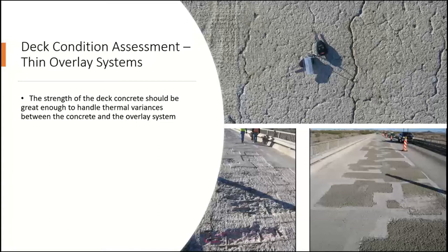We knew that this deck concrete did not have what we thought would be 250 PSI tensile strength, which is kind of an industry standard for concrete strength to retain a thin polymer overlay system for a good long time. We knew it then. When they came and did all this patching, we knew we were setting ourselves up for a possible limited life cycle. I went back to the state with a lot of photographs and shared with them why I thought the condition assessment probably wasn't done properly, and why, if they wanted to consider using a thin polymer overlay system as part of their long-term bridge preservation plan, they needed to reevaluate that.